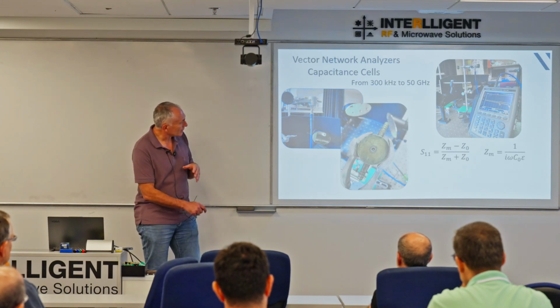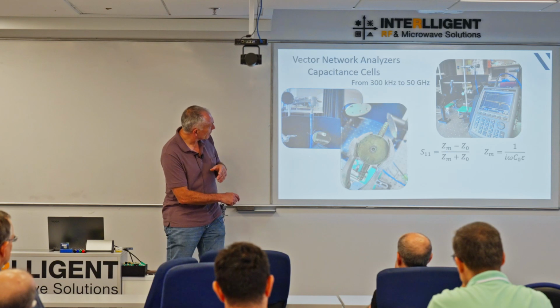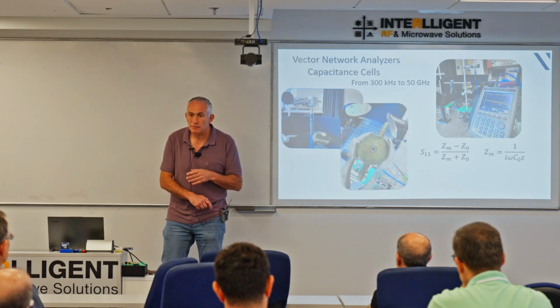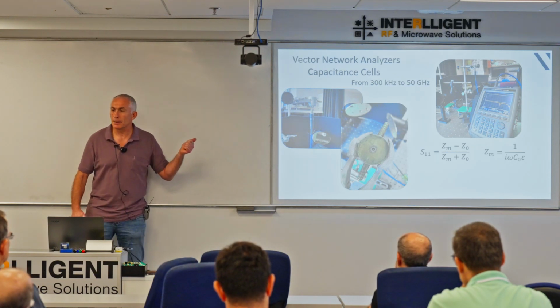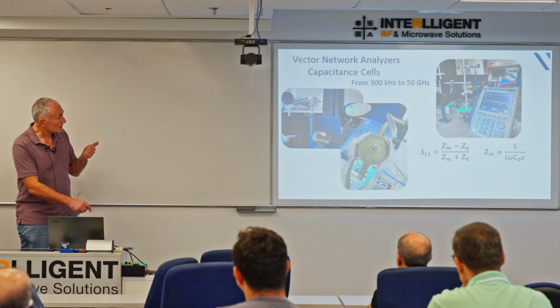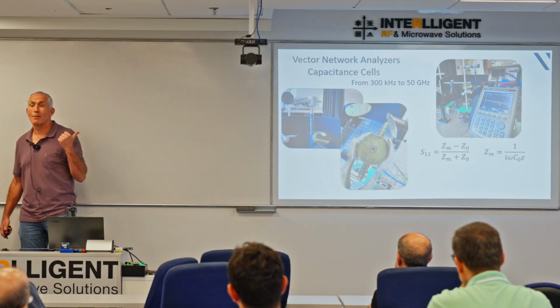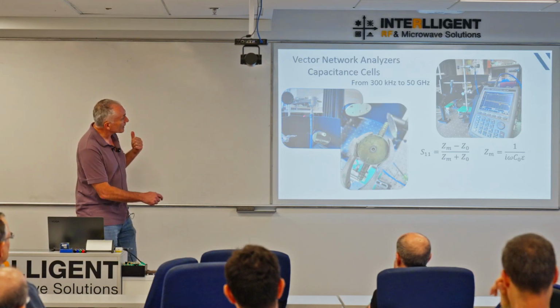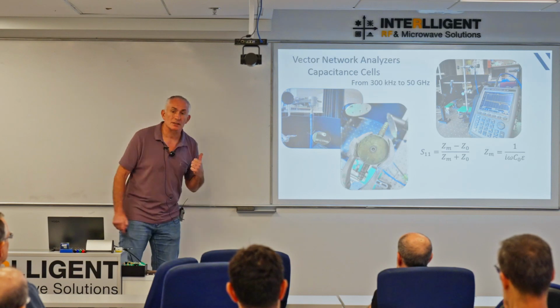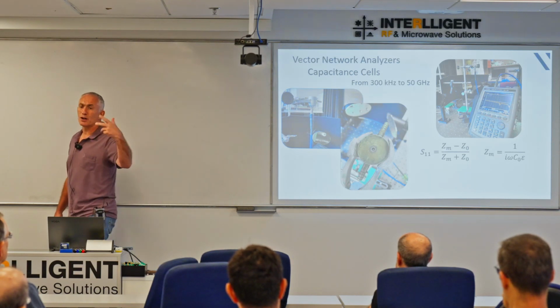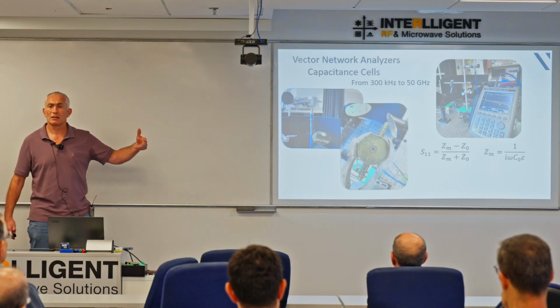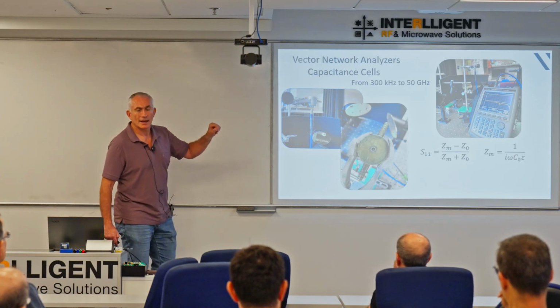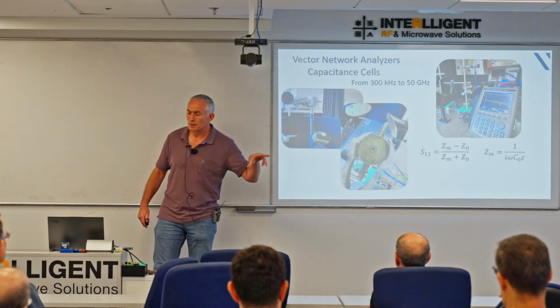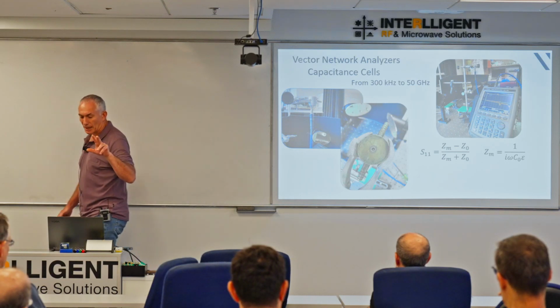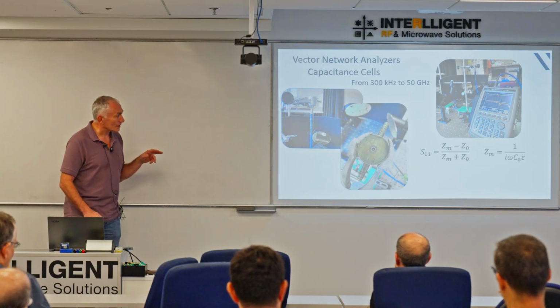So you can see here, this has been calibrated. This is a 2.4 cable with a connector here which is taking it down to an SMA, which means I'm limiting myself up to about 18 gigahertz in this particular case. And it's been calibrated up to the end of this sample cell. And then we're further calibrating by making a short circuit measurement on that sample cell and an open measurement on that sample cell. And from there, trying to get what we get. Okay? Now, how are we going to get it? Very simple.